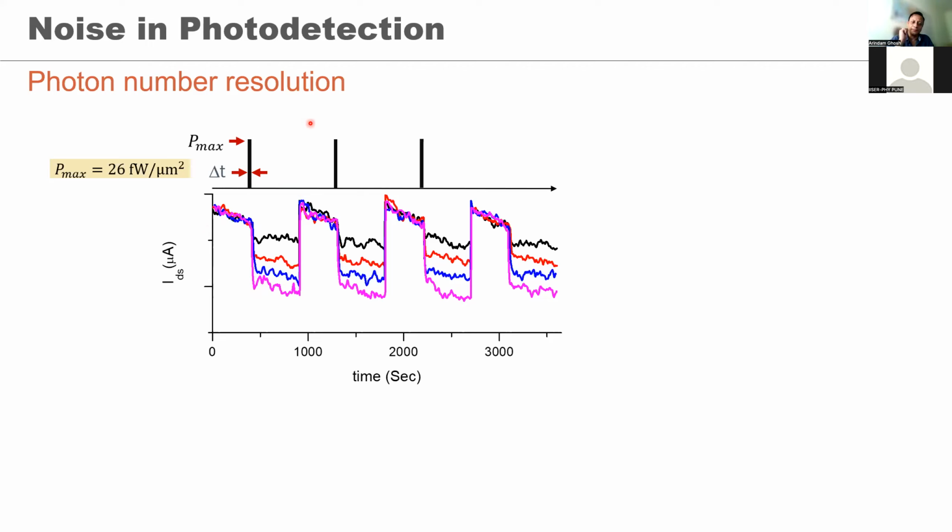But what you do, you send a pulse to the gate voltage underneath, so that now the electric field goes down, and the charge is allowed to come back from graphene into the chalcogen layer, and we recover the old dark state condition, so that I can now apply the second pulse, and this is how the cycle goes on.